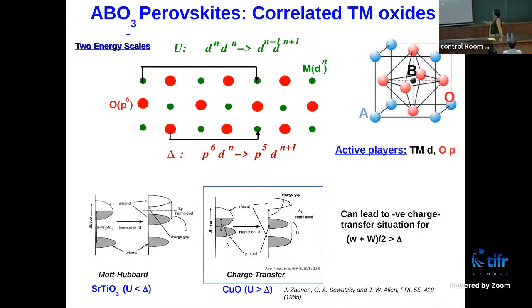And the entire thing is given by a phase diagram, which is known as the Zaanen-Sawatzky-Allen phase diagram. If you are at the early transition metal, early in the periodic table, among these two energy scales, the U is less than delta. As a result, a metal to insulator transition happens by switching on this important interaction parameter U, where the gap opens within the manifold of the transition metal d, in terms of having a subband known as the lower Hubbard subband, which is filled if you are in a half-filled state, and an upper Hubbard subband. Therefore, a metal to insulator transition happens just by turning on this correlation.